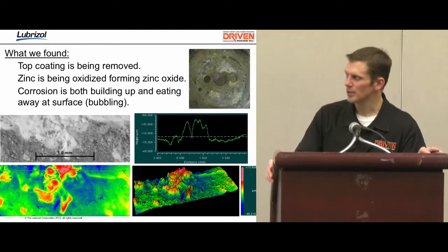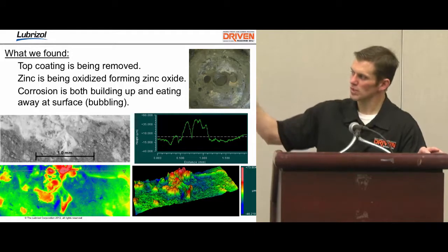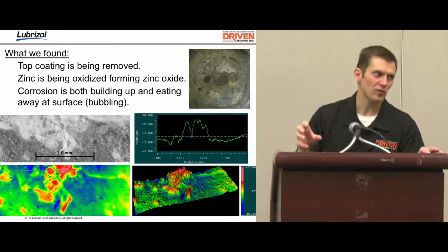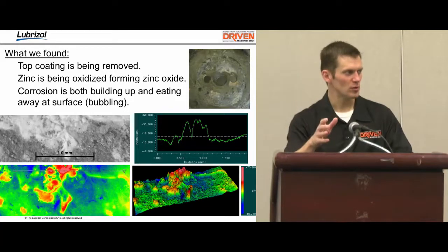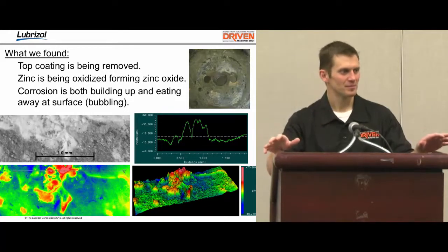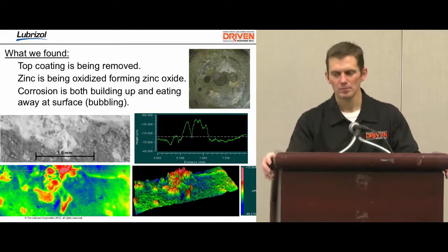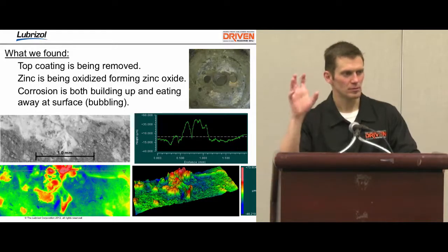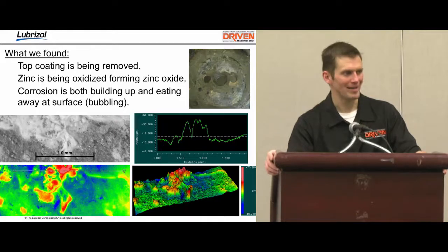And then the temperature factor is because moisture will speed this process up, and the fuels do want to absorb moisture. The hotter the fuel, the more moisture it can absorb. But then when the fuel cools, the moisture wants to separate. Phase separation, which is kind of a buzzword in all this stuff, is a function of temperature swings and exposure to humidity. It's not something that can be prevented. There's nothing you can put in the fuel that will make it not happen.